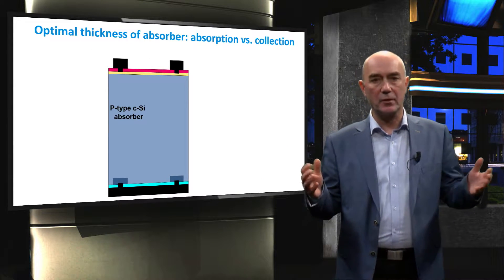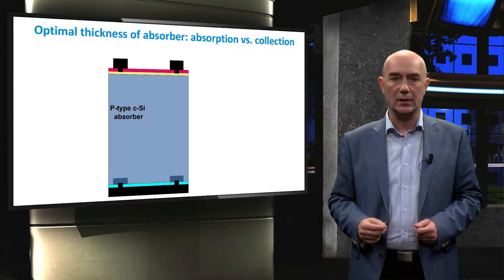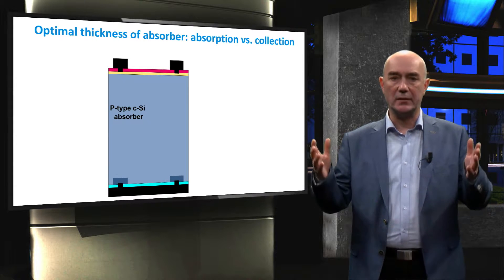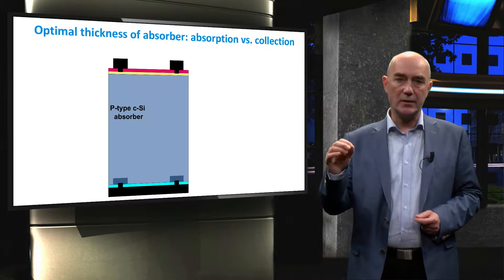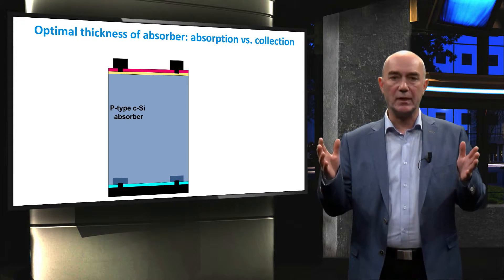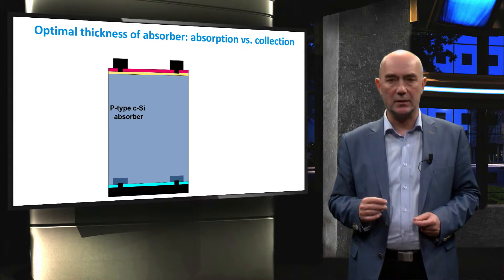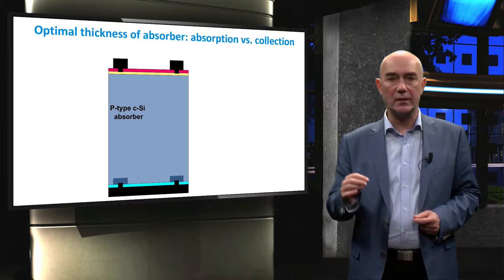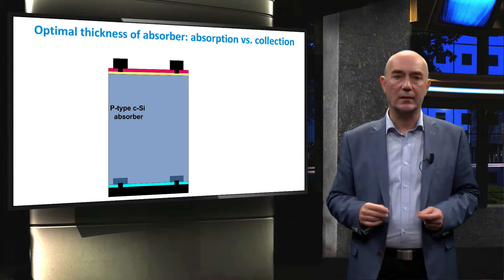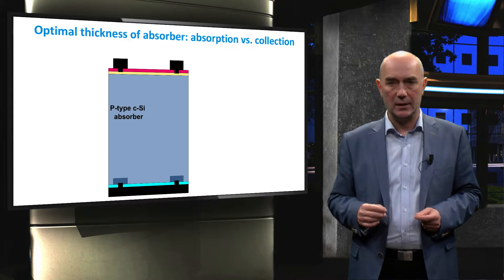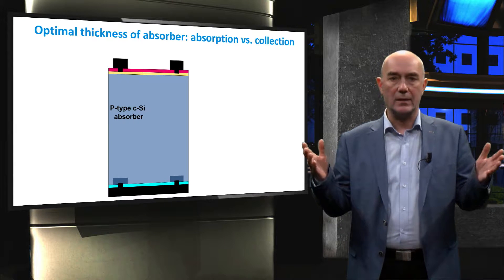The optimal thickness of the absorber layer is a compromise between light absorption and charge carrier collection. Here we see a schematic figure of a typical crystalline silicon solar cell. It is based on a P-type silicon wafer, which is the absorber layer with a normal thickness of 150 up to 300 micrometers. The N-type layer, illustrated in light orange, is called the emitter layer and is much thinner than the bulk P-type absorber — usually in the order of 1 micrometer.